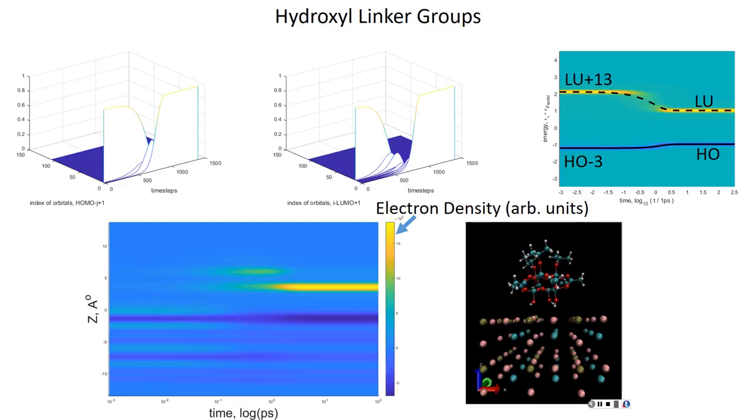In the left bottom figure, you ask why it has both bright and dark spots in one layer. Because both electron and hole are there: electrons are likely on a lead in this excitation, and holes are likely on a bromine. They have different shapes, maybe S on lead and P on bromine, and they coexist in approximately the same space, and therefore there are little fringes, oscillations.